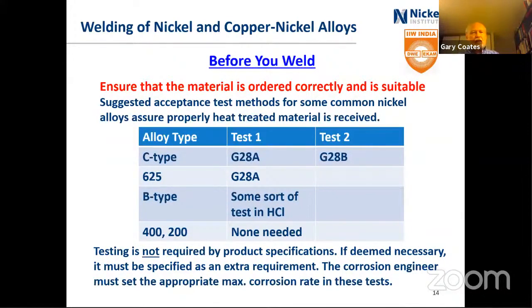And on top of that, we do want to make sure the material is in the best possible condition. And again, the ASTM specification, if you just order it to the standard one for plate, doesn't require any sort of acceptance test. So many chemical producers, and I'll just name people like Dow and BASF, will specify an acceptance test for the material. The acceptance test, for example, for C types and 625 is a G28A test to be done. However, there is no acceptance criteria given in that ASTM spec. So the end user really has to come up with their own criteria.